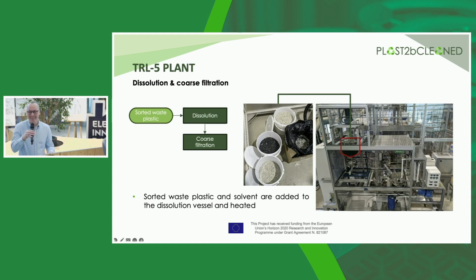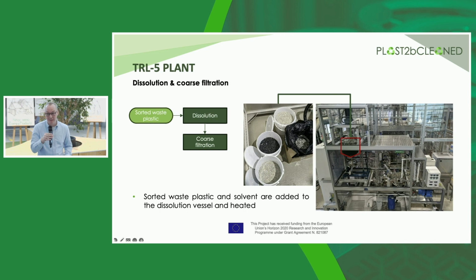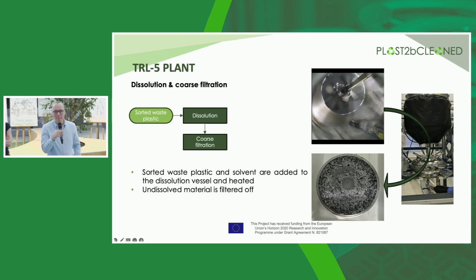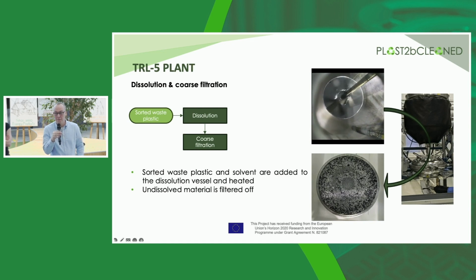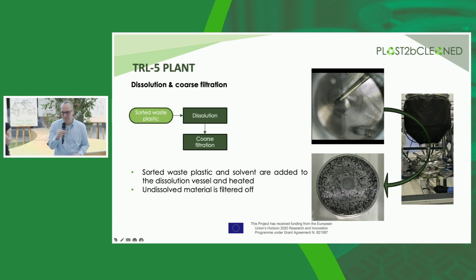And I just want to take you along the journey of how we processed everything at our TRL5 plant at Fraunhofer. We used sorted waste. You can see different buckets there, because they were from different starting material. In the end, we mixed them in specific ratios to be as close to reality as possible. We performed the dissolution on it, so we used the sorted waste, put it in the reactor, added the solvent, closed everything, heated it up. And as you can see, it dissolved, and there will be a video starting, the top side video. There you can see the dissolved material leaving this pressure tank, and what's nice to see is that there is no gelation, no gel formation, no residue within this reactor, which is a good sign for a possible process routine there.